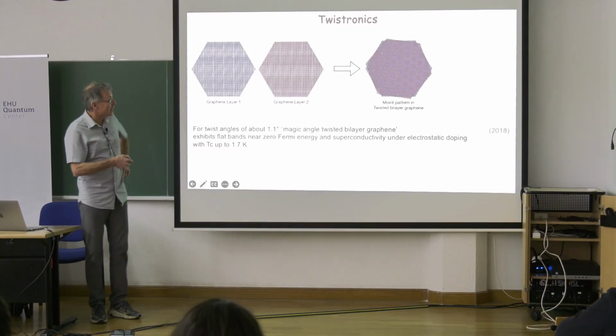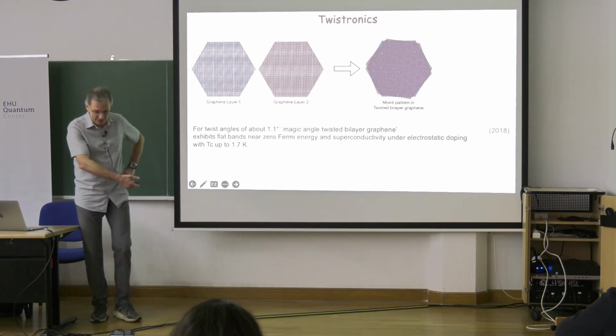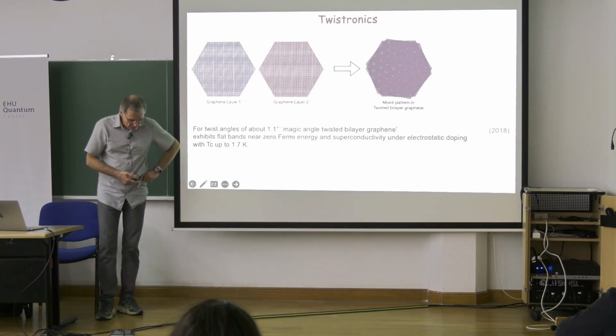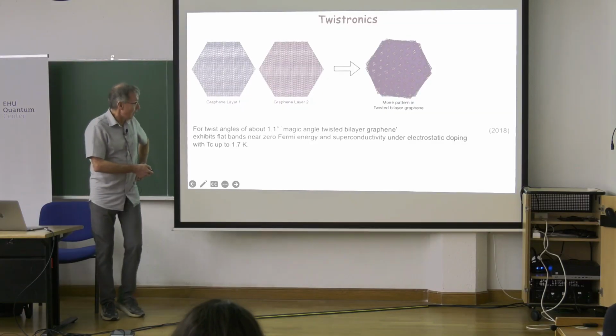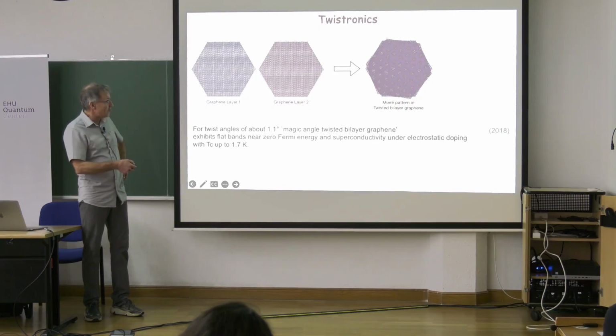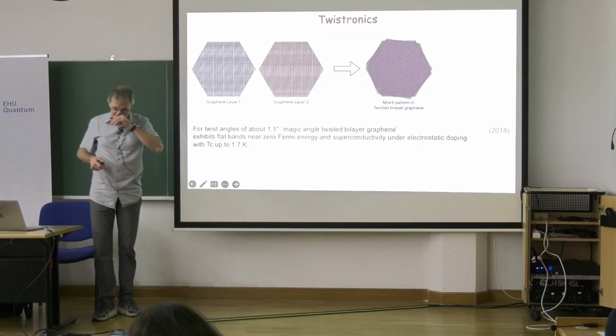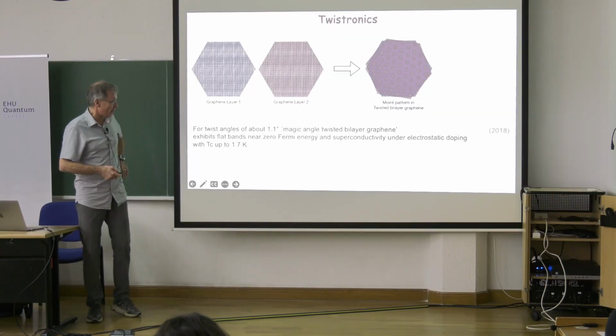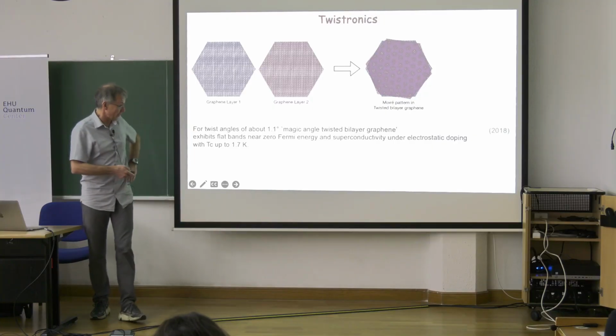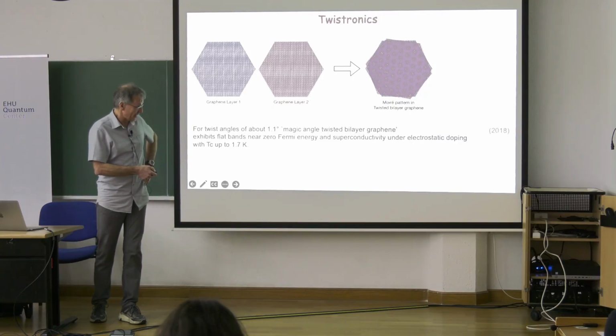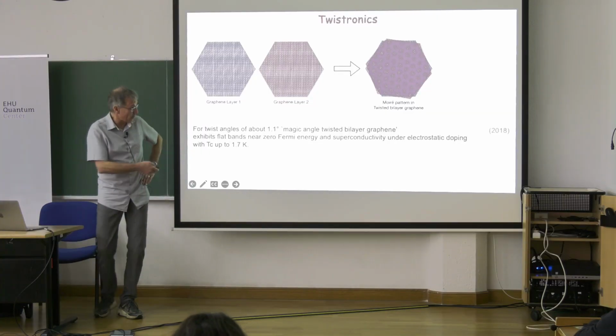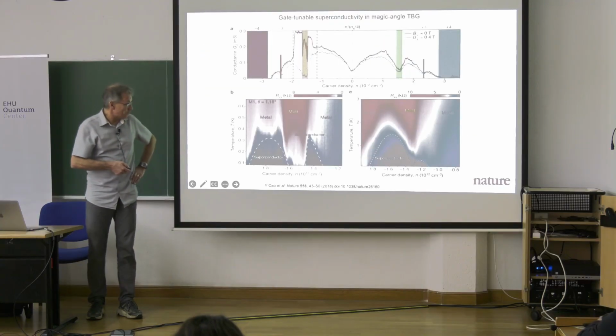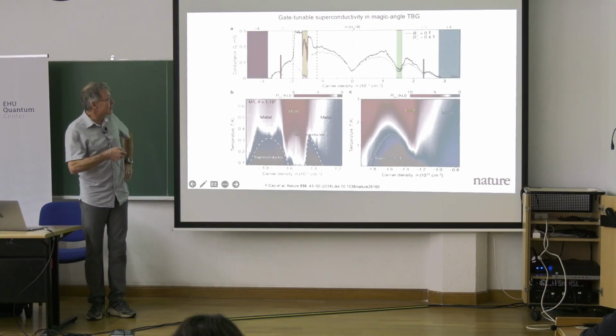If you calculate the band structure, it was first calculated numerically by Allan MacDonald and Bistritzer, who proposed that if you twist at a special, so to say, magic angle of about 1 degree, then you will have so-called flat bands, where the spectrum is very flat and the effective mass is very large, and you may have very interesting phenomena there, including superconductivity. This was, I think, 2011 theory paper, and in 2018, people at MIT actually realized this.